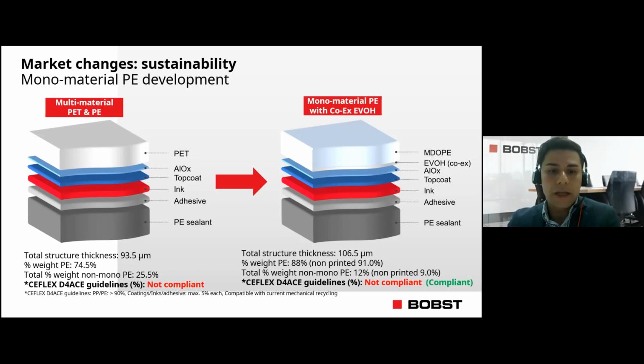On the right is a partially compliant monomaterial PE duplex structure, which is a like-for-like replacement for the structure on the left. The reason why MDO-PE was considered instead of PET was firstly to mimic the mechanical properties of PET. The machine direction orientation process improves tensile strength, stiffness, and optical properties. An EVOH skin layer of a few microns, which is co-extruded, offers good receptiveness for metallization.